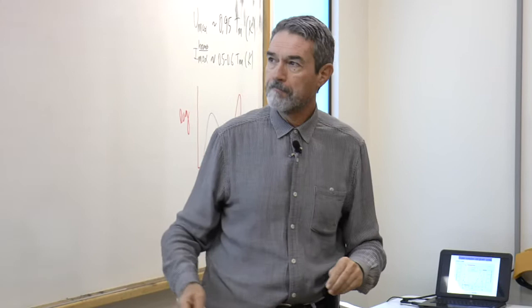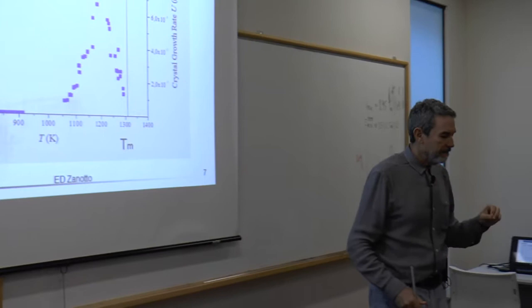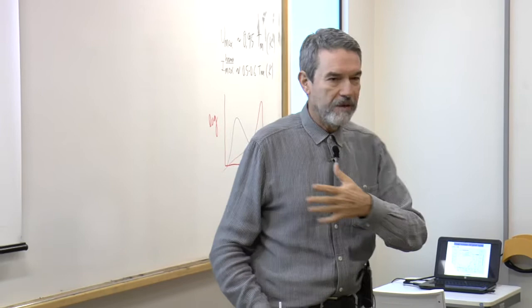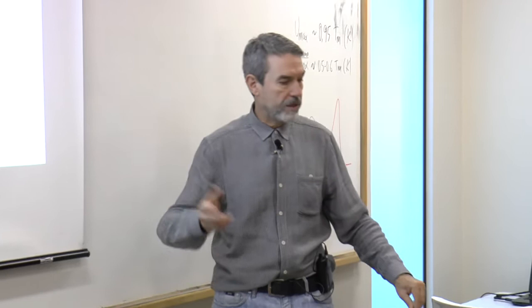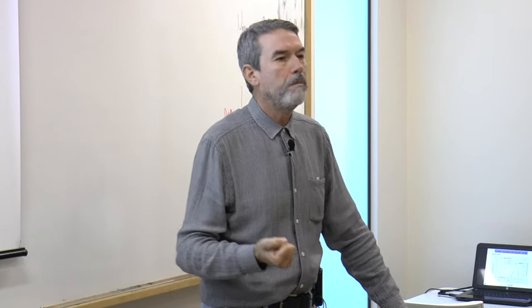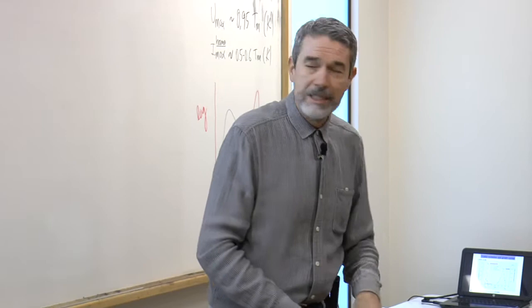Right, and this we think is homogeneous nucleation. I have some arguments to try to convince you that we are dealing with homogeneous nucleation, because every time I give a seminar about crystal nucleation in glasses to a non-expert community, they ask, how do you know that this is homogeneous nucleation? Because homogeneous nucleation is not thermodynamically favorable. Heterogeneous nucleation on bubbles, on scratches, or impurity particles is much more favorable. So people ask, how can you be sure?